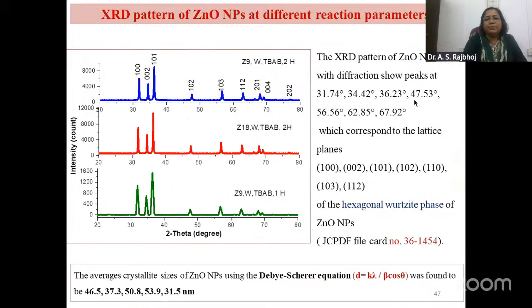Then we have the XRD pattern. The size of these particles can be found by using the Debye-Scherrer equation, and we can also determine their shape. You can see here hexagonal wurtzite particles of zinc oxide nanomaterials have been found, and the sizes are near about 46.5, 37.3, 50.8, 53.9, and 31.5. So this is the average crystallite size of the zinc oxide nanomaterials.